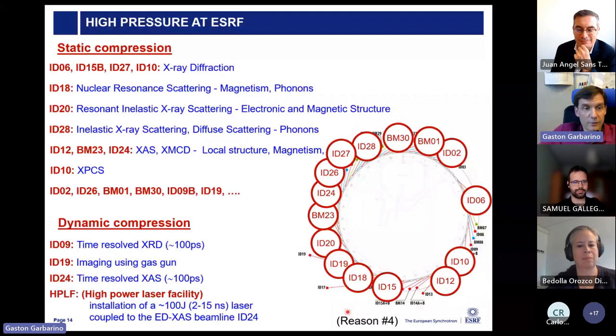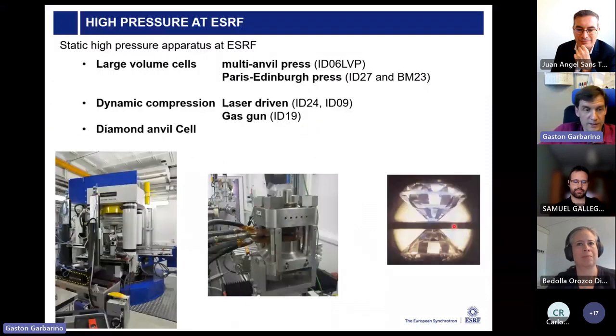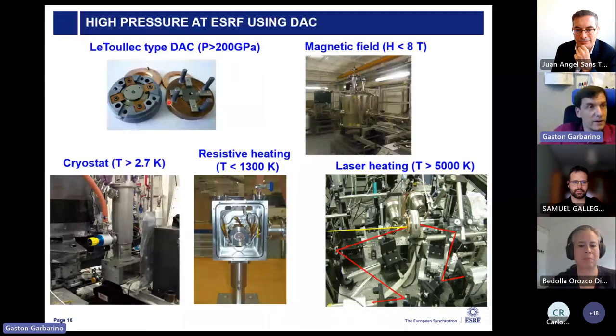There are different types of high pressure cells that we have at the ESRF. I will mostly concentrate on the diamond anvil cell, as I said before. This small device is roughly the size of my hand, 50 millimeters in diameter by 30 millimeters thick. It can be coupled with a cryostat to cool down, can be heated up with resistive heating, or we can couple it with lasers and really reach very high pressures and temperatures. At the same time, if we do it non-magnetically, we can couple it with high magnetic field and pressure.